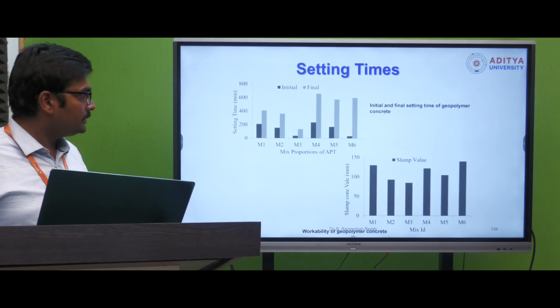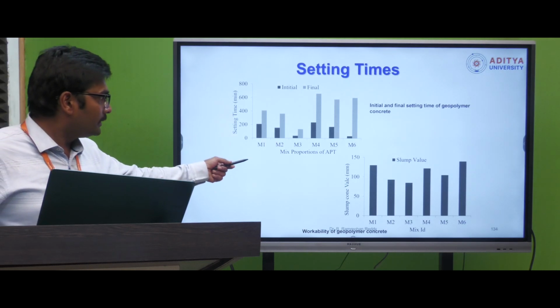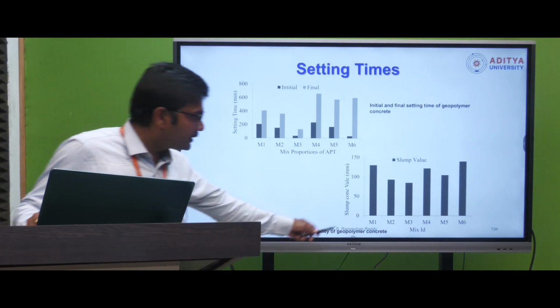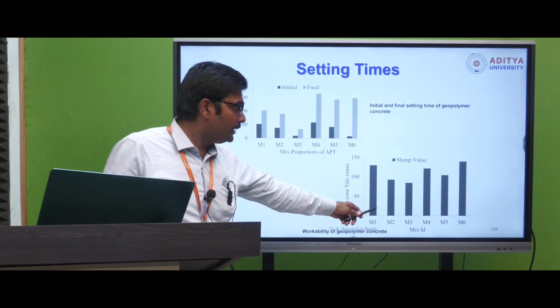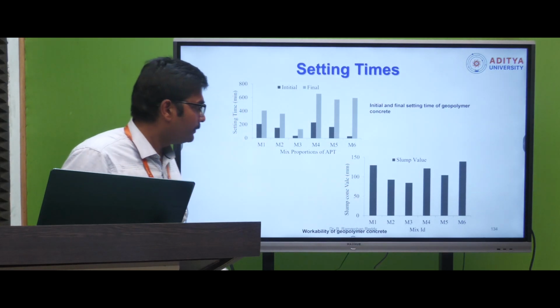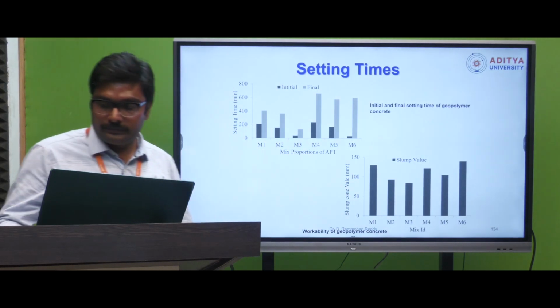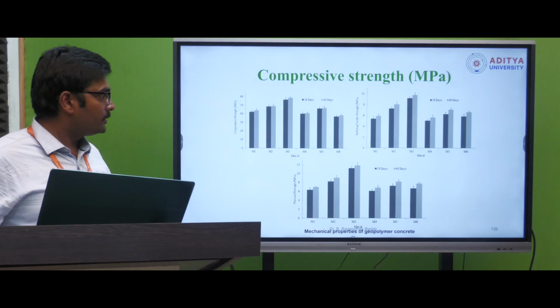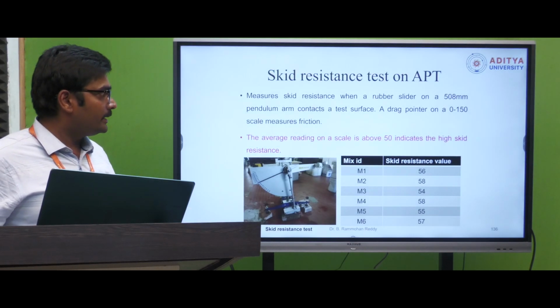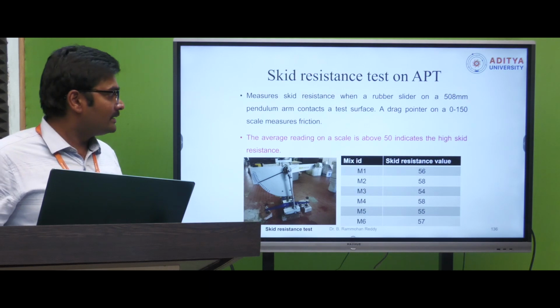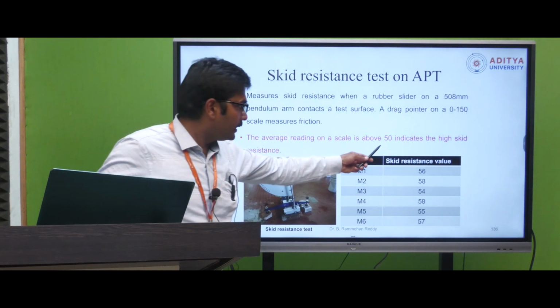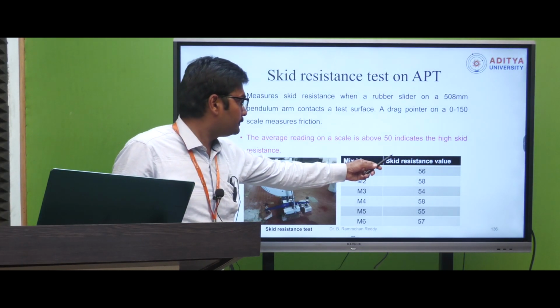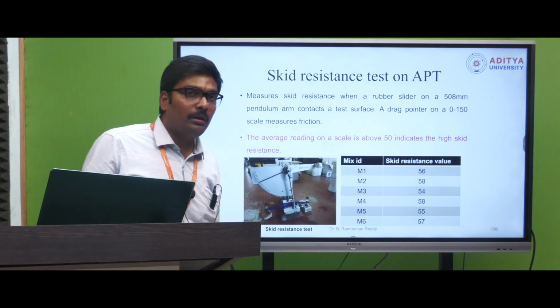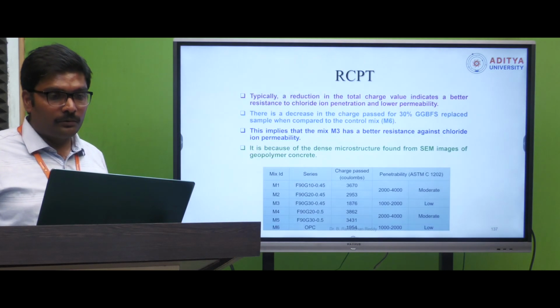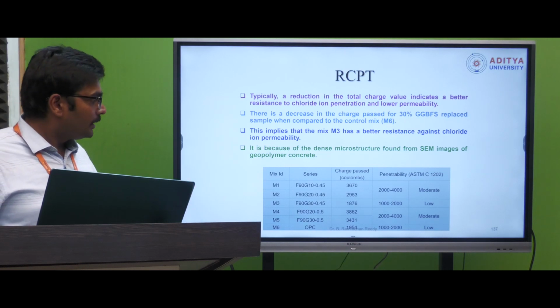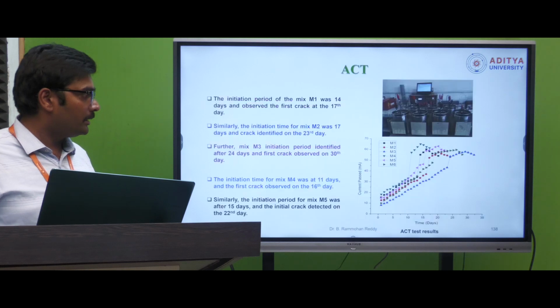And these are the indications: by increasing the GGBS content, the setting time is reduced, both initial and final setting time. The slump value is also reduced by increasing the GGBS content in the sample. And if we increase the solution to binder ratio, the slump value is increased. Similarly the compressive strength. We have done the skid resistance test on the APT, because if it is a road, skid resistance is also important. The average scale here indicates 50 and higher, which is a good resistance, so all geopolymer concrete mixes produced better results towards skid resistance. And RCPT, as I said earlier, the RCPT values are good for the geopolymer concrete as compared to the conventional.